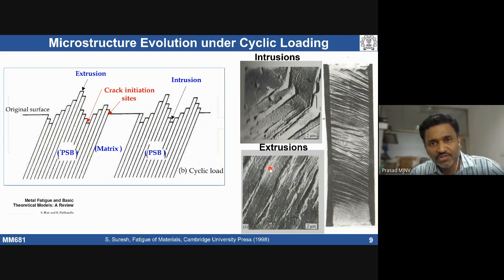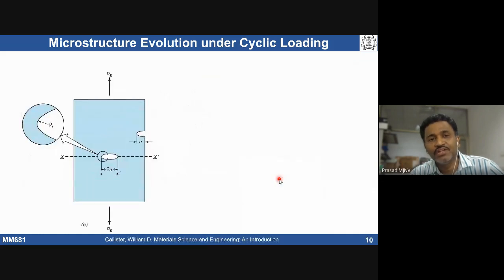This is another microstructural feature, though at a different magnification. We may see this formation of hills and valleys on the surface, which indicates that a cyclic deformation activity has happened in the material. Even if my applied stress is below the yield stress, if I assume there is a minute crack that has been initiated, that crack can lead to further deformation around the crack region.